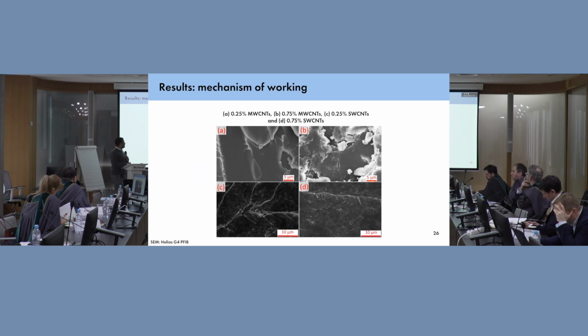to SEM. On the screen are, for multi-wall, lower weight percentage, higher, and lower is single wall for the same weight percentages. So we see our carbon nanotubes. We see that the percolation network here is a bit weaker. For our multi-wall at 0.75, the percolation network is a bit better. This is why we see the difference in electrical properties and the lower and higher piezoresistive response.